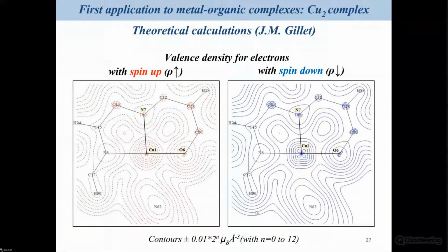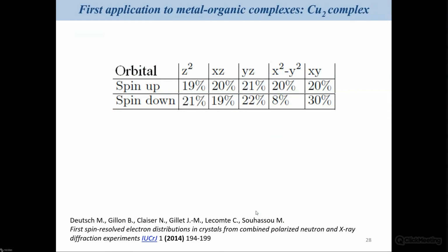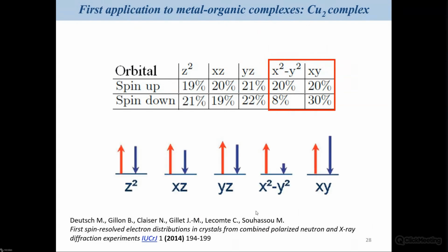You have very similar distribution of spin up and spin down around the copper atoms. You can also project the model you have for the spin distribution around the copper atoms on orbitals, I mean the d orbitals of your copper atoms, and obtain distribution of spin up and spin down that indicates that you have something which is very homogeneous for the spin up, but it's not the case for the spin down, with the dx²-y² orbital and the dxy orbitals that are clearly not homogeneous in terms of spin down population. And then it gives you a kind of representation of what is the spin distribution on the copper atom in the system.